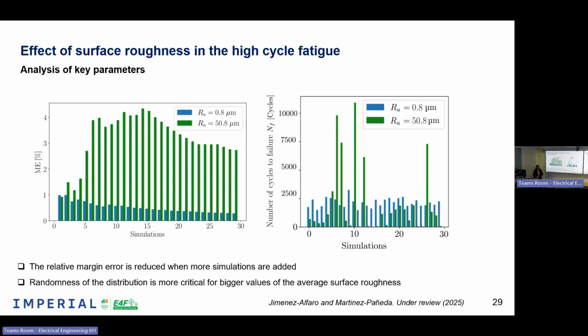We have also represented the evolution of the surface factor in a sample. Here you can see the margin error for different simulations. As soon as we increase the number of simulations, the margin error is being reduced. Moreover, we can see that for bigger values of the average surface roughness, this margin error is much bigger. It changes a lot. Looking at the number of cycles that we can predict, it can be even dangerous because here we have selected a load level just to have an expected value of around 2,000, 3,000 cycles. And you can see that for very big values of the average surface roughness, in one case we can have 2,000 cycles, in the next one we can have 10,000 cycles. So we don't know. This is the key point of randomness.